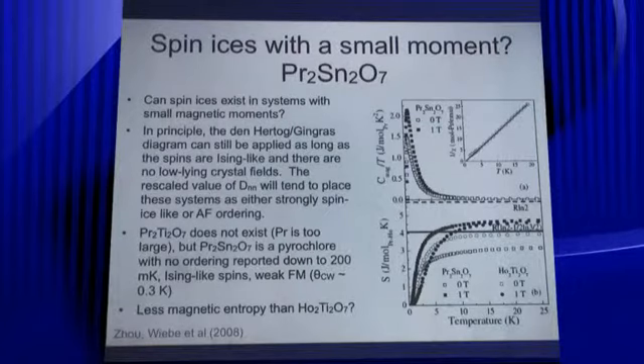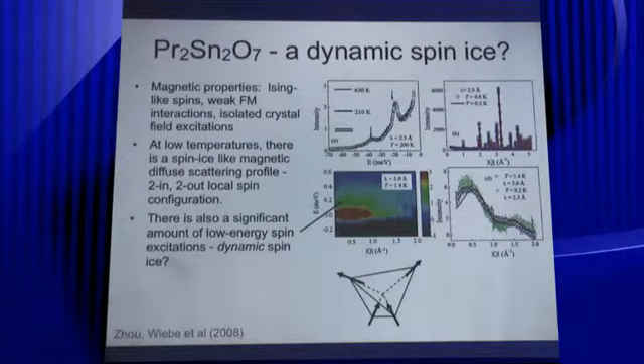So what's happening? Is it a spin ice or is it not? Well, you have to look at some other probes, look at this with neutron scattering. So we first showed there was no ordering down to 200 millikelvin with neutron scattering. And we did some inelastic spectroscopy, so we found there were well-separated crystal fields, on the order of around 200 Kelvin or so. Looking at the elastic scattering, we saw this characteristic sort of spin ice-like profile. This red fit is to just a spin ice model that we use, and there's some missing intensity at low Q that I'll mention on the next slide. So it's not the best model, but it looks like on the elastic time scale anyway, we have this 2-in, 2-out configuration on each tetrahedron.